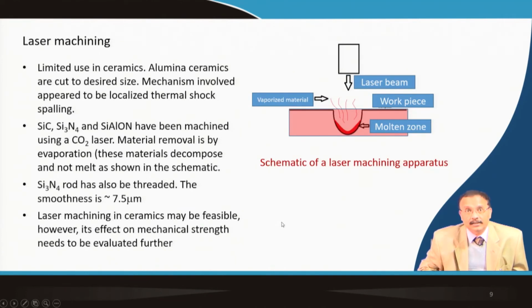Laser machining is actually limited in the case of ceramics, but in alumina ceramic laser machining has been done. The mechanism is localized thermal shock resulting in spalling for material removal. Usually silicon carbide, silicon nitride, and silicon aluminum oxynitride, Sialon, are machined by carbon dioxide laser. Material removal is by evaporation.